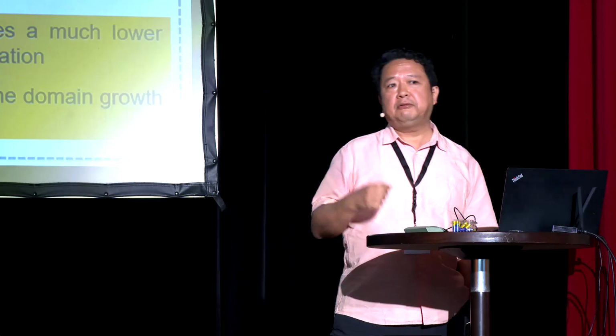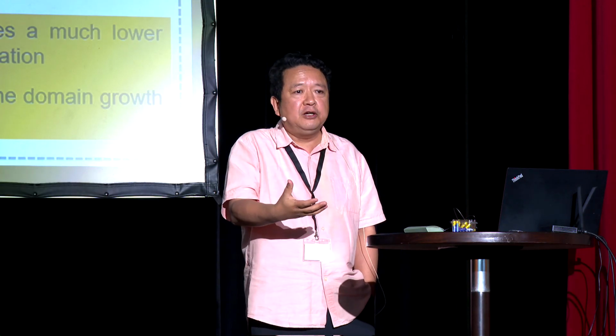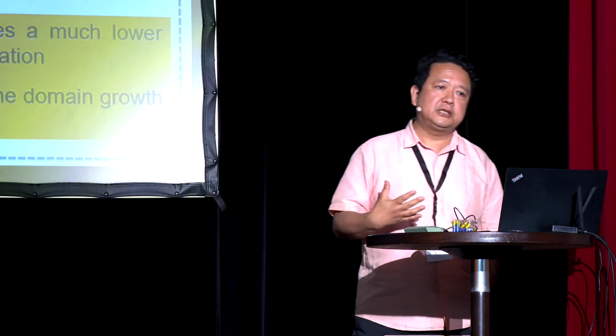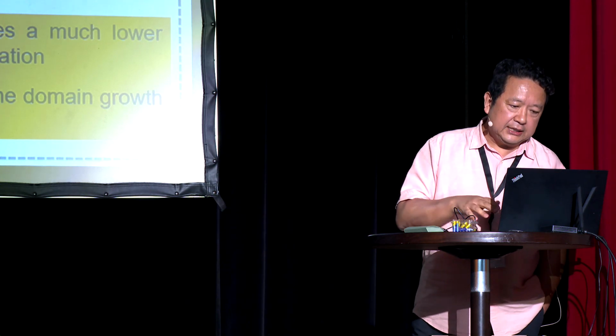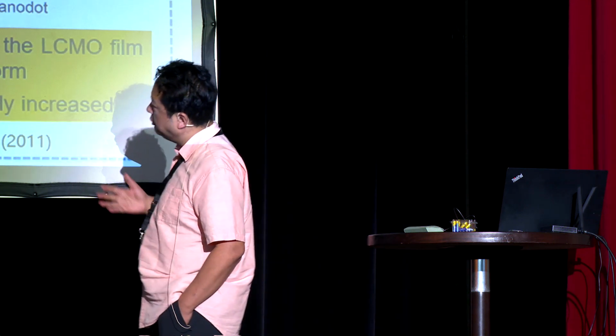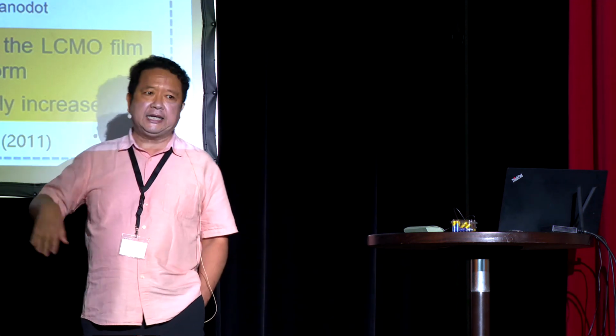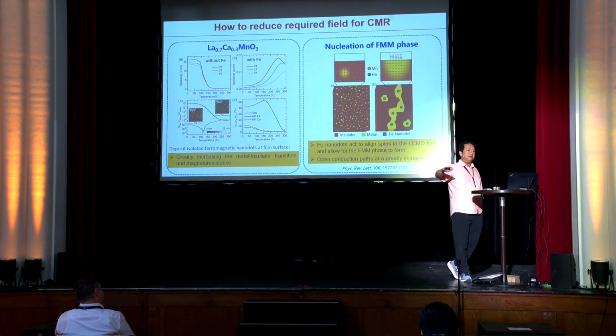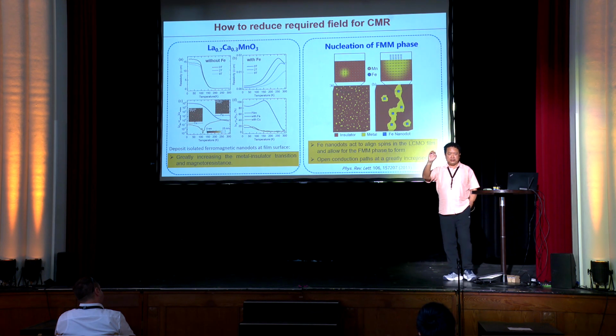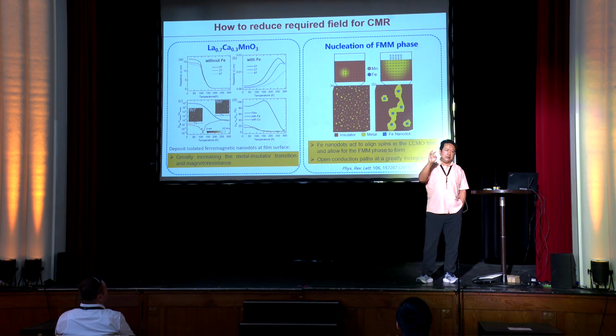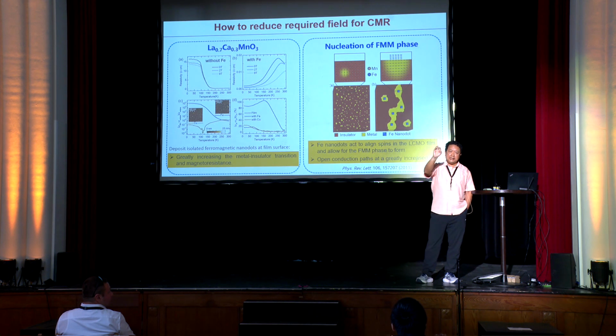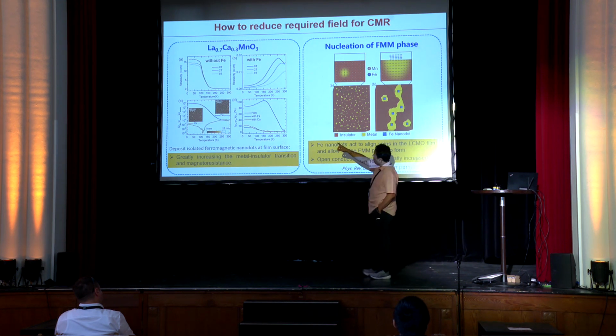If we can do that, then we only need some small magnetic field, to boost this domain growth and reaching this CMR effect, right? And the way we can do that, in fact, from our old work, is that we put the magnetic nanodots on a manganite thin film. We find that the exchange field provided by the magnetic dots with the manganese spins underneath is enough. Actually, this is an enormous field, right, the exchange field, that can convert the regions below this magnetic nanodots into the ferromagnetic metallic phase. So you can see the effect is very dramatic.